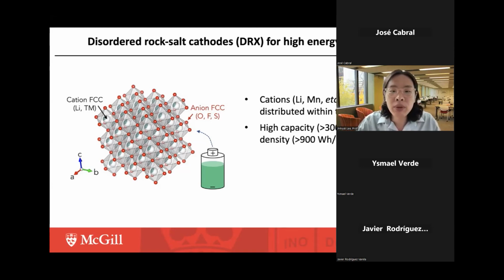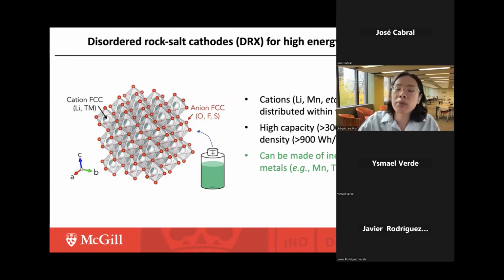Interestingly, this material can deliver very high capacity above 300 milliampere hour per gram and very high energy density above 900 watt hour per kilogram, which are much higher performance compared to the traditional nickel and cobalt-based cathode materials. And finally, the most important part is that these DRX materials can be made with many different types of inexpensive and abundant transition metals, such as manganese, titanium, vanadium, or iron. So considering both the inexpensiveness and the high performance, these DRX materials are a few classes of materials that can actually bring a substantial improvement to lithium-ion battery development.